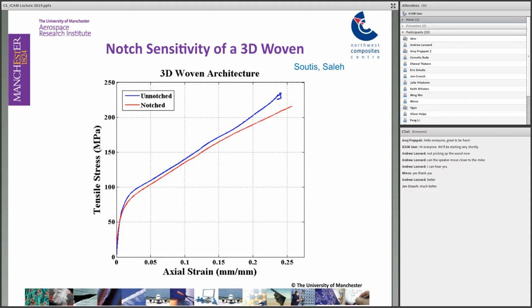So here, what we can see is that we have removed material from our plate in the form of damage, and that damage doesn't affect the tensile behavior. It affects very little the stiffness, and it doesn't affect the ultimate strength and its ductility. So some progress there has been made.